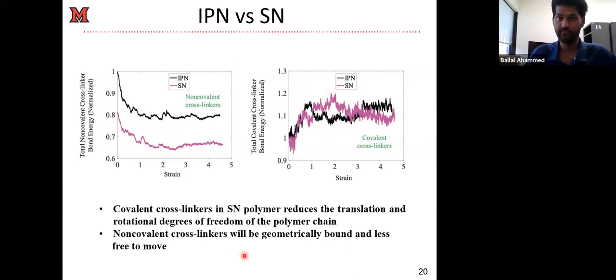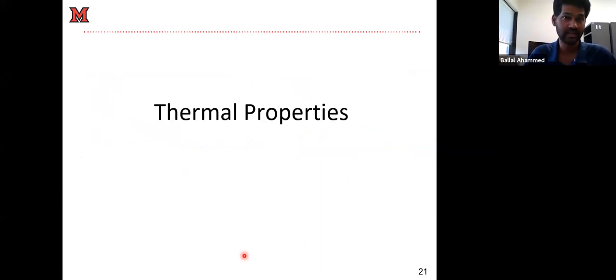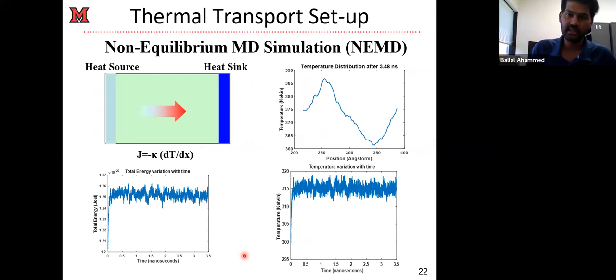Then we did some thermal properties study using molecular dynamics for our case. So let's look at a couple of our studies for the thermal case. For the thermal case, it's not an ideal playground for coarse-grained molecular dynamics simulations for heat transport, because you lose a lot of degrees of freedom. So in this case, your thermal conductivity will not match with the experiments. We didn't even try to do experiments on the thermal transfer measurement, but we are able to get some trend right for our case.